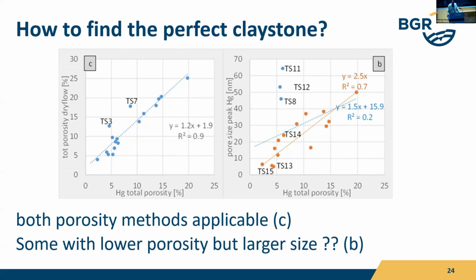And then looking at the right side, we have the total porosity on the x-axis and the pore size on the y-axis. The pore size in case of claystones is actually reflecting the average distance of the particles. So the main pore volume of claystones are not the pores you see directly in the SEM. It is actually the distance, or the space between the particles. And there are a lot of very small particles, and it is hard to resolve these pores, even by electron microscopy. But they make up to 80% of the pore volume, right? And by mercury intrusion, you can accurately measure this distance, obviously.